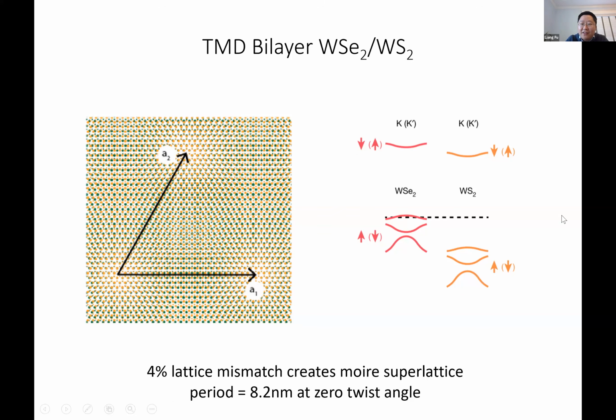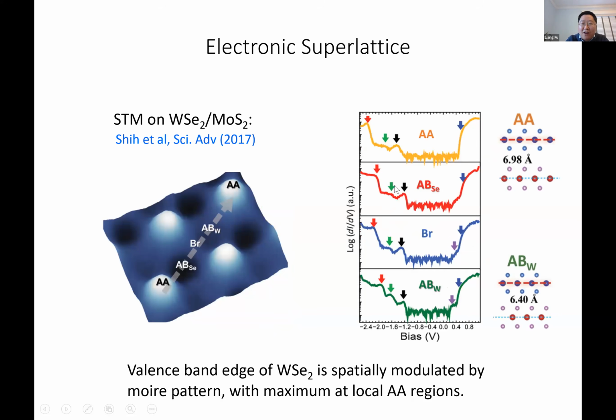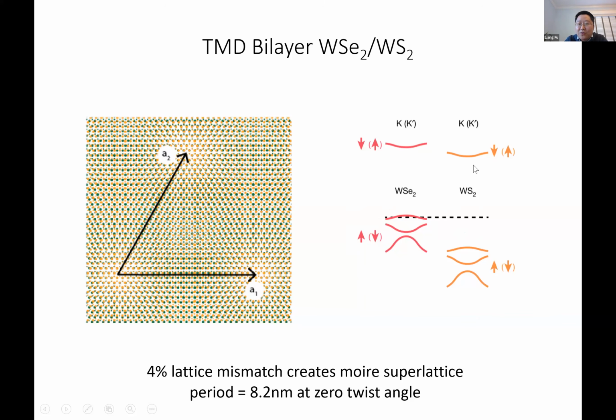And so here, the schematic figure shown on the right shows the band alignment of the 2 layers. And we see that the topmost valence bands are in the WSe2 layer. So in other words, if we have a small amount of doping, the holes live on the WSe2 layer. Okay. Now what the other layer does is to modify the electronic property to form an electronic superlattice, to turn the holes in the WSe2 layer into an electronic superlattice.